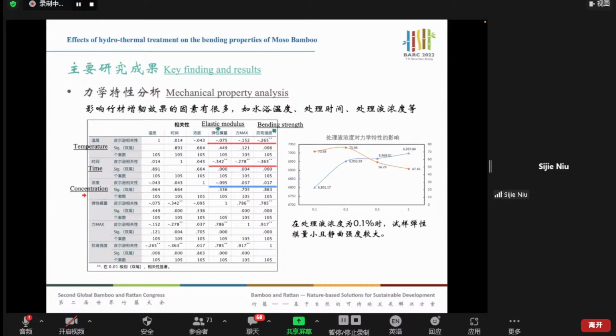So we use some solution treatments, and we also use water bath treatment method. Based on the different temperature, you can see the concentration level, the differences with regard to elastic modulus and bending strength. It's negatively correlated to the temperature and the concentration. So with a longer period of higher temperature treatment, bamboo can become more flexible. But there were no matured treatment solution being seen.